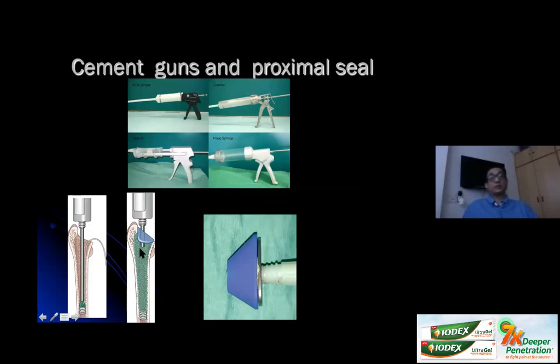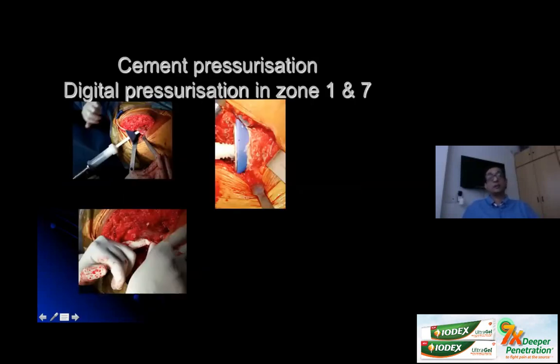Then you remove your vent and pressurize the cement further. When you pressurize it well, on the surface of the bone, you will see some amount of fat escape out from the bone, which is a sign that you are pressurizing it quite well. After this, I generally tend to pressurize zone 1 and zone 7 with my thumb and a little finger, so as to get good cement penetration there. Because if you just use the femoral seal, sometimes in zone 1 and zone 7 you might not see a good amount of cement. So go ahead and digitally pressurize zone 1 and zone 7.